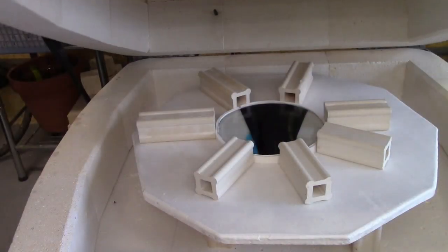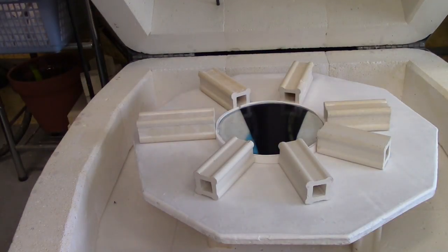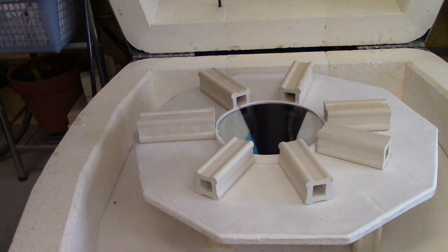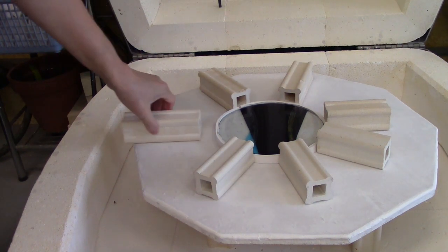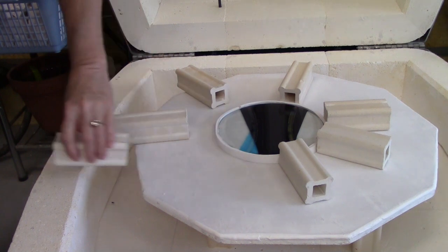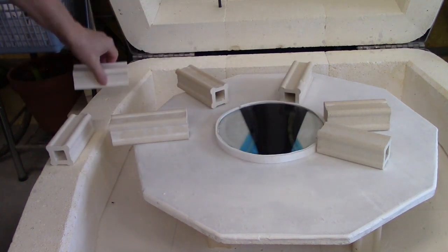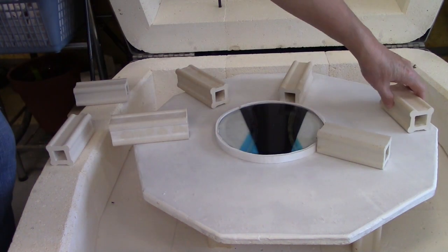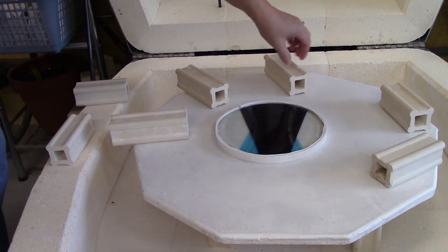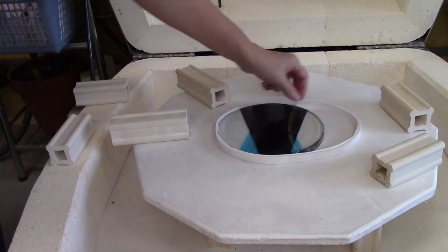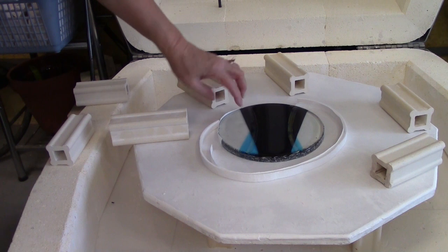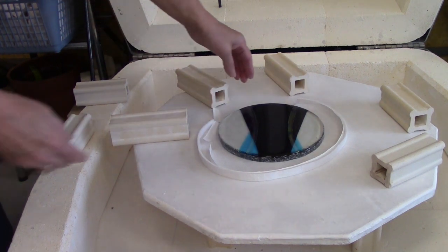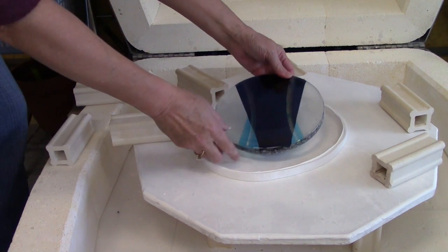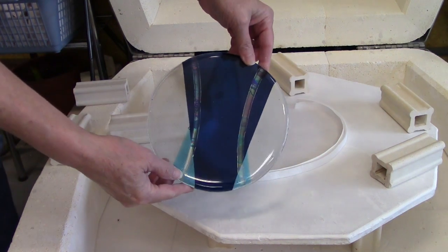So we're going to fire this to a full fuse temperature, and here's the piece coming out of the kiln. Remember, I like simpler is better on this type of construction, but of course, you can get as elaborate with your pattern and design as you'd like. This was fired on a primed ceramic kiln shelf. I used thin fiber paper, and then 1/8 inch thick fiber paper to contain the glass. And I held that paper in place with kiln posts.